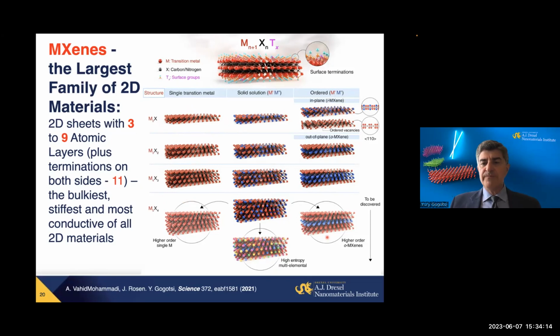Single element, solid solution, high entropy MXenes where 4-5 different metals are mixed in the structure randomly, or this type of higher order MXenes with twinned 5-layer structure, or out-of-plane ordered atomic sandwiches, I call them, or in-plane ordered materials. Or if you etch away one of the elements from in-plane ordered materials, you get basically rows of monatomic vacancies, double vacancies on the surface. So again, sky is the limit for sure. So we are really moving to a new era of atomistic design of materials with MXenes.